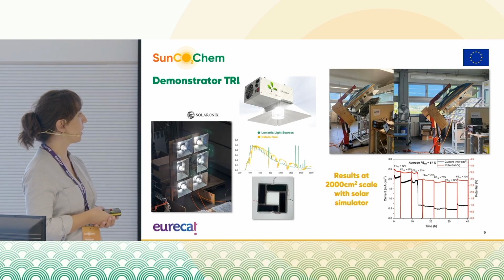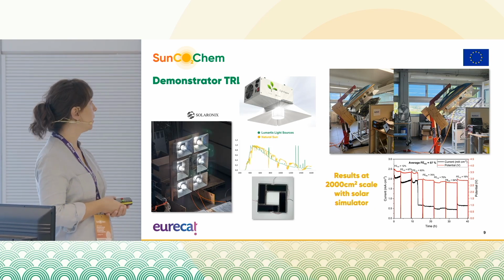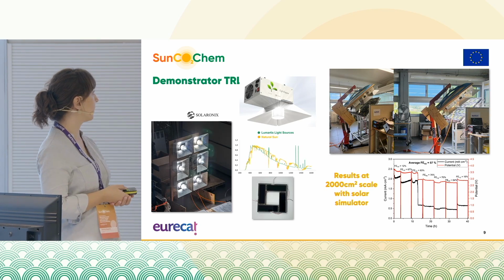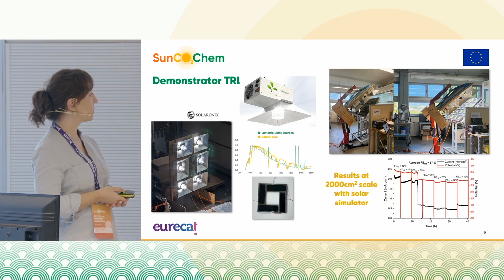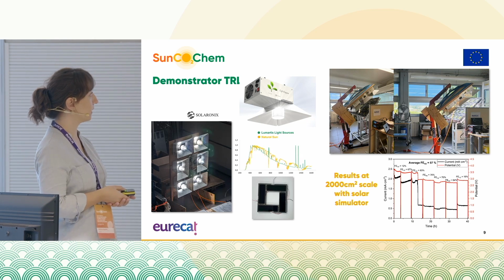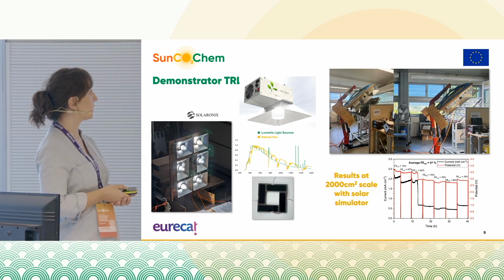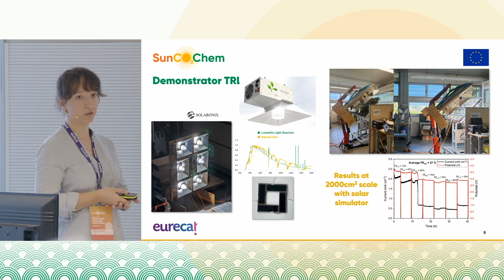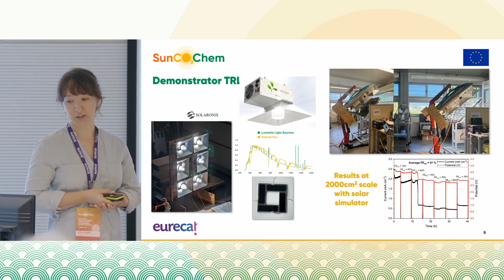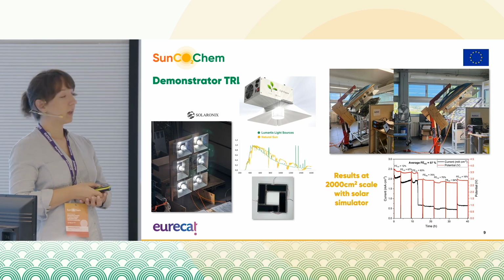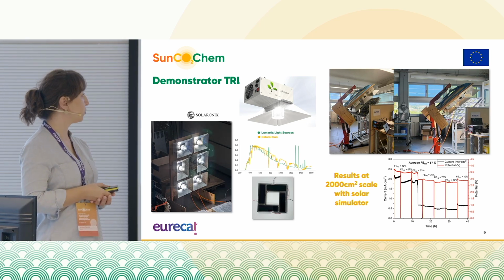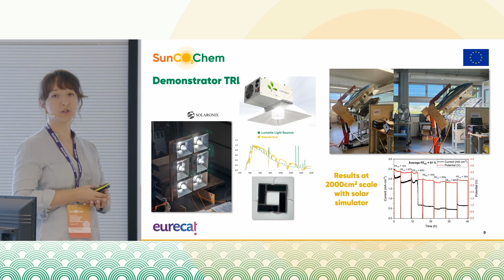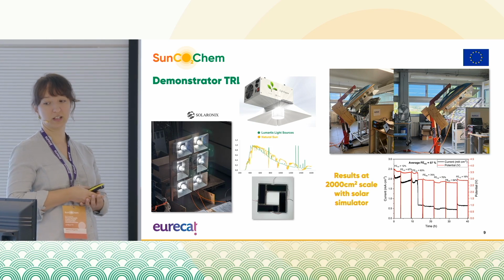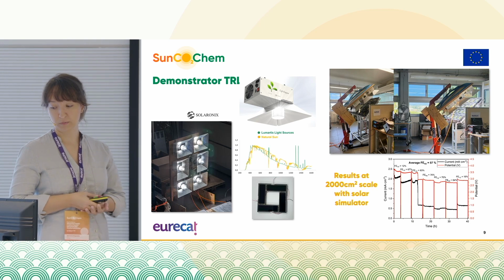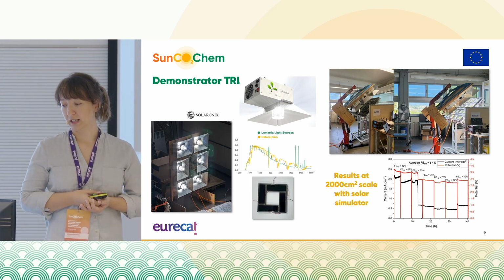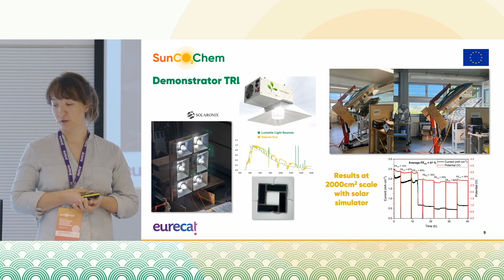And we moved to the testing of the entire reactor using a sun simulator that was provided by Solaronix. Additionally to the photoanodes, we also used PV panels that were also specially designed for this reactor in order to supply more energy, but always sun energy, to the reactor. We tested it at a 2000 square centimeter scale, which is to our knowledge the biggest photoelectrocatalytic reactor that can convert CO2. However, we saw that the reactor was mainly producing hydrogen.